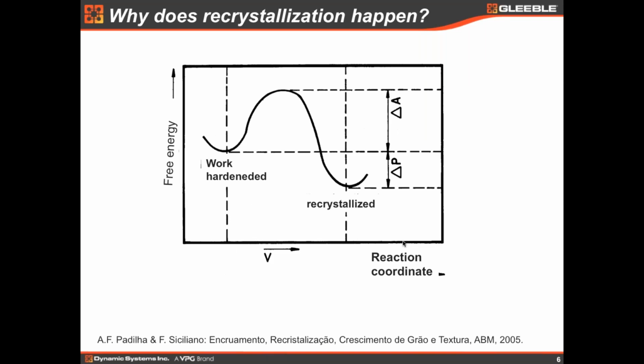Why does recrystallization happen? This is an important question. In the work hardened state, due to the defects, we have a higher free energy, and in the recrystallized state, with a very small amount of defects, we have a lower free energy. So if we give thermal conditions to that system, the work hardened state will overcome this activation energy and will recrystallize. So this is an energy view of the recrystallization transformation.